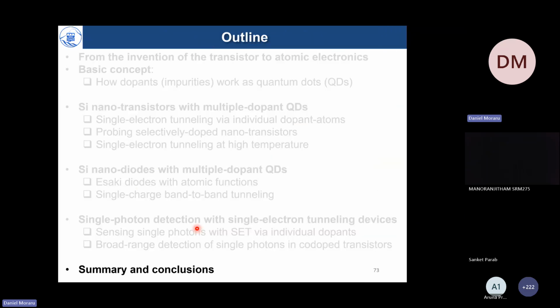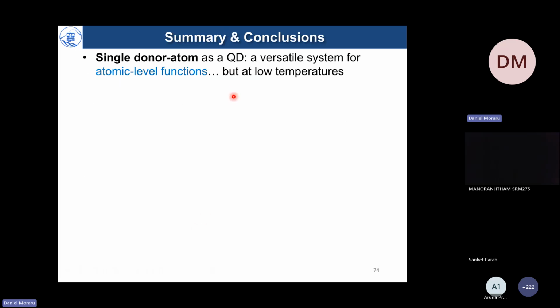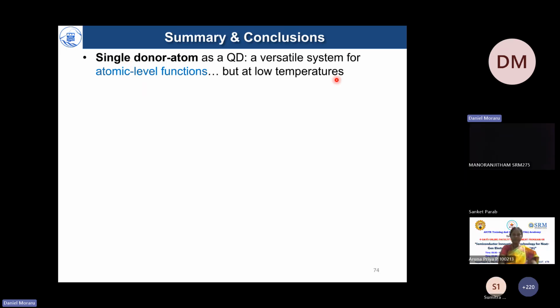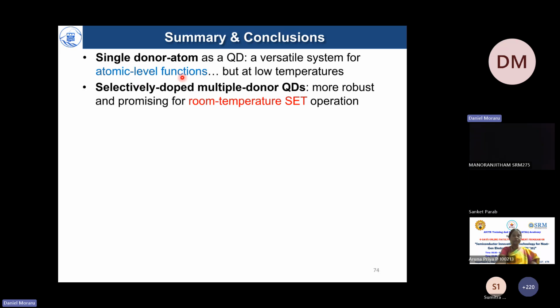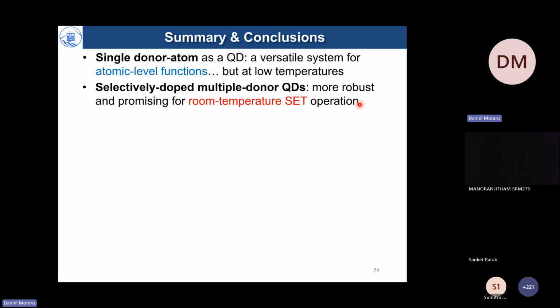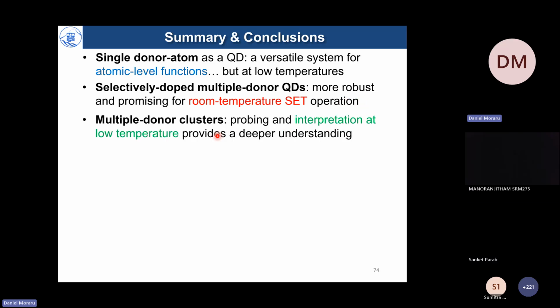So I took probably a little bit more than I should for the time, but I'm going to leave you with the following summary. Single donor atoms are indeed a versatile system for creating atomic level functionalities, but we have to stick to low temperatures. Raising the temperature is really challenging. Selectively doped multiple donor quantum dots can work for room temperature SETs. We demonstrated that, and they are more robust, but they are not atomic level functions. We have to discard that concept.